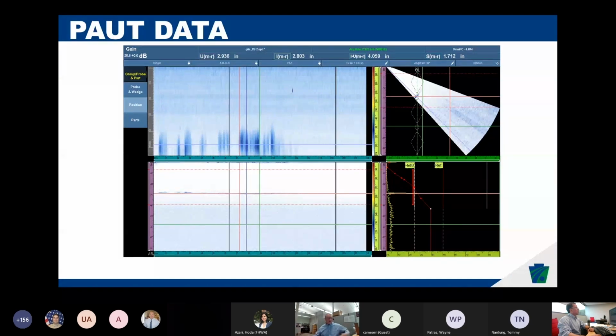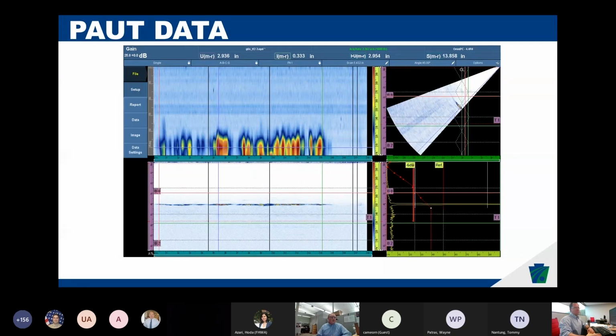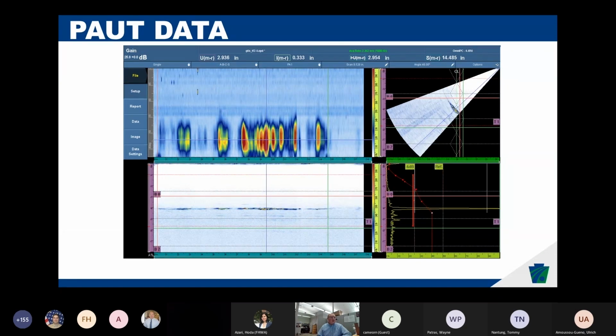So looking at the phased array data, like I said, there's 4 different files, 4 different scanning offsets, 4 different locations. You can see here you get the different imaging views. You get the plan view, you get the side view, you get the sectorial view, and you still get the traditional A scan output. So for this particular scanning index offset, it didn't find the full radiography rejected flaw, but it found part of it. And that's the purpose of doing the different scanning offsets. So looking at it from a different point of view, or different scanning offset, it did find primarily the whole indication, as well as another index offset.